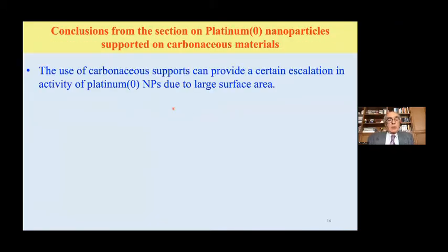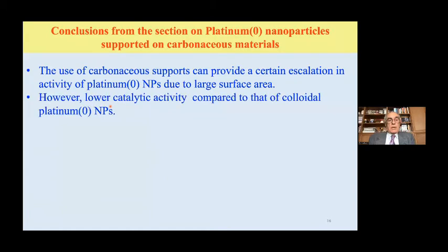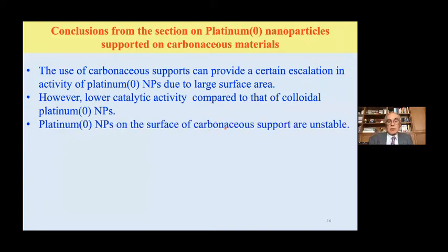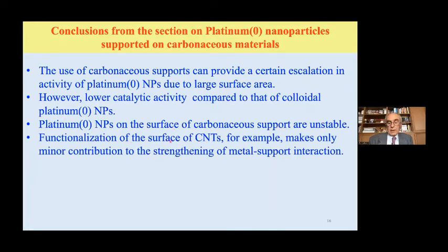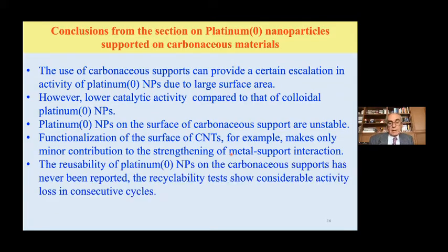Conclusion here, the use of carbonaceous supports can provide a certain escalation in activity of platinum nanoparticles, maybe because of the large surface area. However, the catalytic activity is lower compared to the colloidal nanoparticles. Platinum nanoparticles on the surface of carbonaceous support are not stable because of the weak metal support interaction, obviously. Even functionalization of the surface of carbon nanotube makes only minor contribution to the strengthening of metal support interaction, and therefore it is really not usable. And reusability of platinum nanoparticles on the carbonaceous support has never been reported. However, the recyclability tests show considerable activity loss in consecutive cycles.